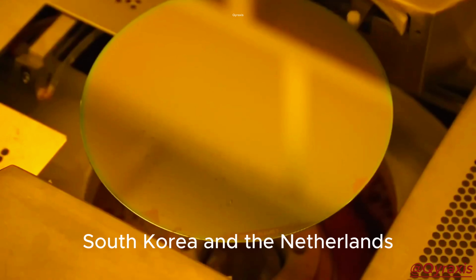The exposed photoresist is dissolved away, leaving a pattern of open trenches in the resist layer. Those trenches define where the next process step will act on the silicon beneath. Etching removes material from the exposed areas. Dry etching, the dominant method at advanced nodes, uses plasma generated from gases such as fluorine or chlorine compounds at pressures between 1 and 100 millitorr. The plasma bombards the silicon surface with reactive ions, removing material with dimensional control down to 0.5 nanometers per etch cycle. A single transistor gate stack may require 12 to 15 separate etch steps, each targeting a different material layer.